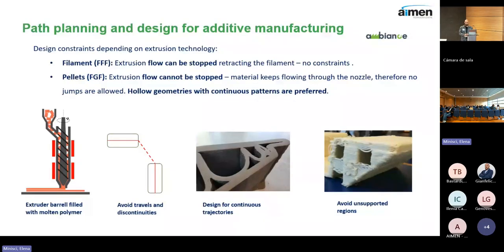So if you are not printing and you lift up the extruder head, it will pour through the nozzle. So in this situation, you should avoid making travels and discontinuities between the walls, aiming to design for continuous trajectories. You should integrate, for example, the infill into the design, and you should avoid unsupported regions, because this is another key difference with filament extrusion: you don't have the possibility to use support material here. So there are other strategies to not use support and successfully print features like ceilings.